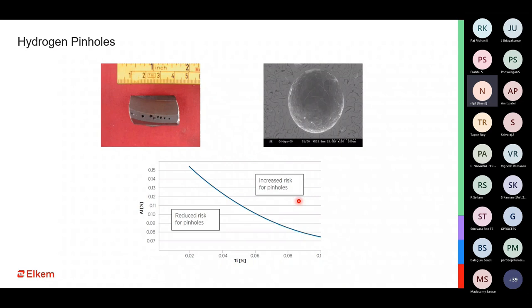Sources for aluminium and titanium. Titanium can come in from your raw materials. Titanium can come in from your ferrosilicon sources. Titanium can come in from your scrap or the returns. And aluminium can come in from your steel scrap, and also from the ferroalloys that you use. You could be using high aluminium containing ferrosilicon, ferromanganese, or even inoculants and ferrosilicon magnesium. So the aluminium sources and the titanium sources need to be controlled to reduce the risk of hydrogen pinhole in the system.